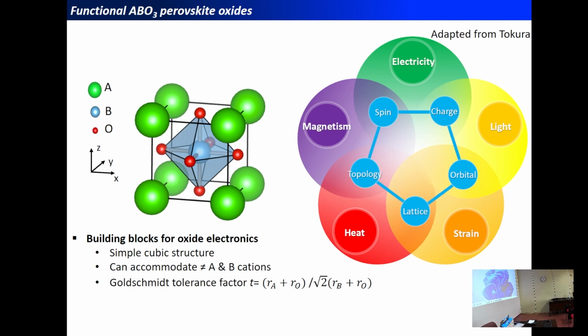Among all the oxide materials, the most famous ones are the ABO3 perovskite materials, which adopt in the ideal case a perfectly cubic cell in which the A-site cation is at the corner, and the B-site cation is at the center of the cube, surrounded by 6 oxygen atoms forming an octahedron. These oxide perovskites are really appealing because they can accommodate almost any A and B cations in the material.